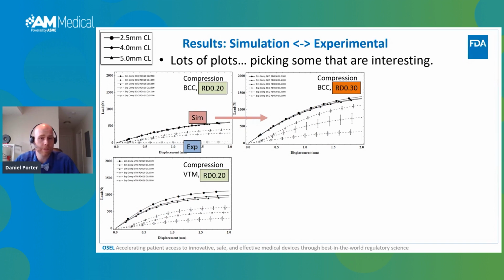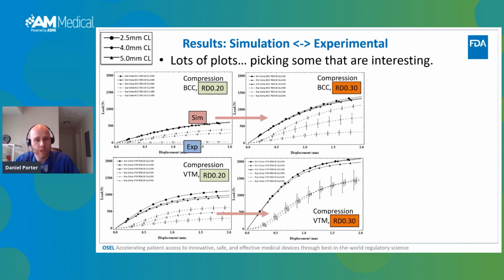What we found that was interesting for this, though, is when we actually jumped up to a relative density of 0.3 for these Voronoi, which are stochastic lattices, this happened. So the smallest strut diameters actually increased their stiffness. And I should throw in that this is when the pores of the lattice are the smallest. For this design selection, the smallest strut diameter had just over the required pore size to facilitate powder removal in the general situation, given our system setup choices such as powder mixing ratio and things like that.